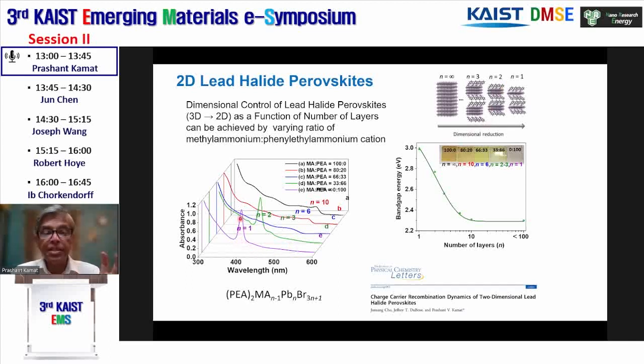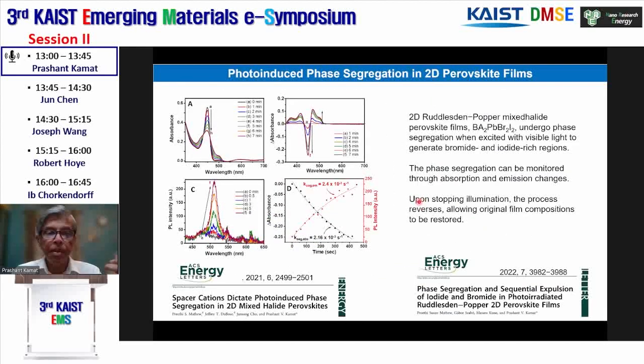So the interesting point here is the sharp excitonic peak that you see for n equal to 1, 2, and 3. And beyond n equal to 6, it behaves more like bulk. And as is evident from this plot of binding energy versus number of layers, you can see here, after about 6 to 10, there is no change in the binding energy. So they behave more like bulk. And people also call them quasi-2D materials. But most interesting is this earlier region, less than 6, I think.